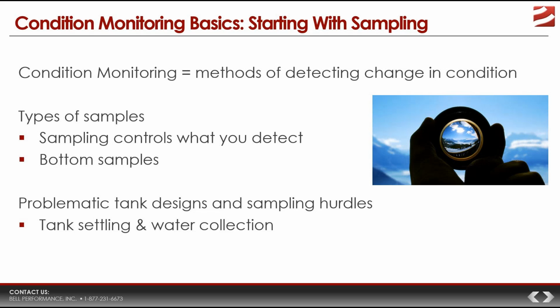Now remember, we said very early on, where and how you sample controls what you can detect. Let's use an example. Most commonly in the retail gas station world, fuel samples are collected from dispensers. And there's reasons for this. It's fast and it's easy. A dispenser gives you a nice, clean fuel sample that is perfect for fuel quality testing. And fuel quality testing is stuff like measuring the cetane rating or measuring the viscosity or measuring the flash point. And all of these are important tests that have definite value in things like verifying that the fuel's in legal specification. However, they're not so good for microbiological purposes.